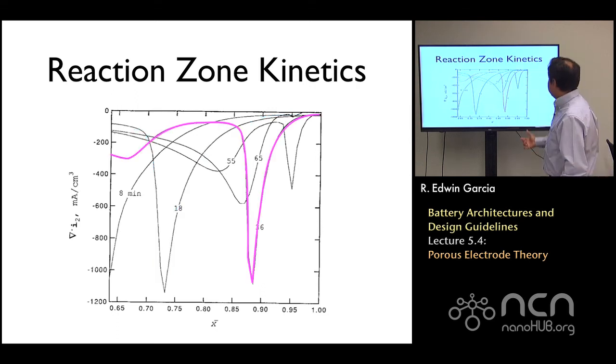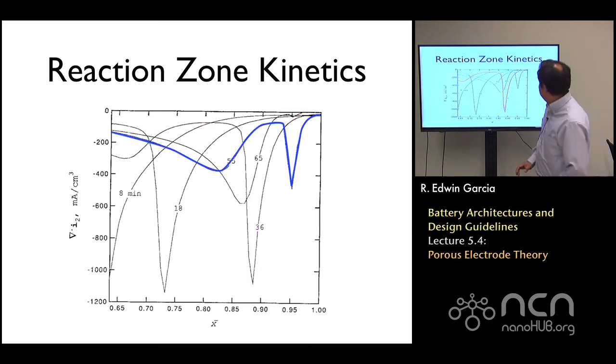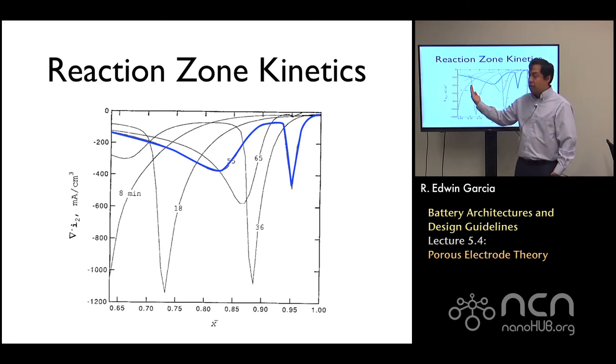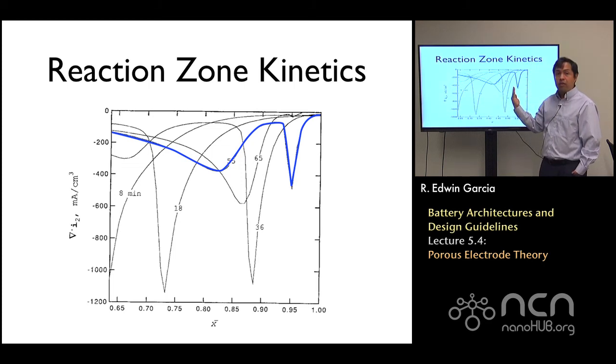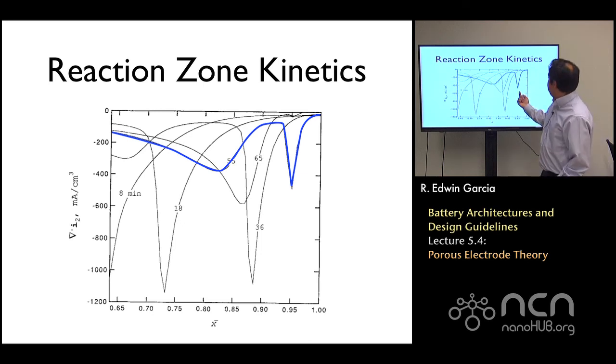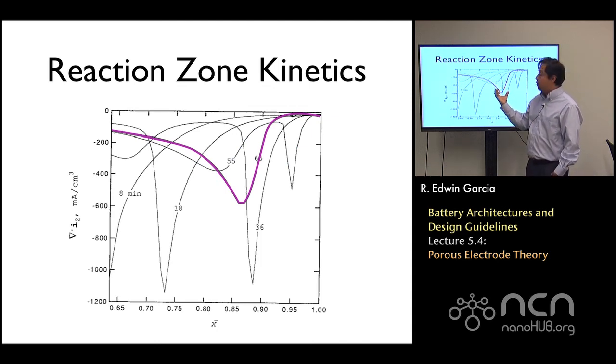Similarly, after 36 minutes, that boundary has migrated deeper into the cathode, and after 55 minutes, you can see here how it has basically reached the back. So effectively, numerically, the system indeed captures this transport, you have this boundary region, this reaction zone that is moving to the back, capturing it very well. Okay, and if you have that, it's interesting to see how the second peak develops, and at the very end, a part of the material recovered, so you get an extra peak back,